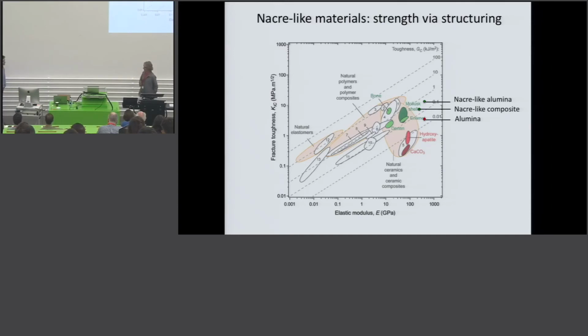Right. So in the case of bone, you also have obviously the challenge of addressing brittleness because you have 50% of the material being hydroxyapatite, right? And bone also uses this concept of structuring the material at different length scales in order to combine strength and toughness, being stiff at the same time being difficult to break. The mechanisms are slightly different in a way that at the smaller length scales you have collagen fibrils, which are oriented in the loading direction, in that sense similar to the seashell. And these are reinforced with hydroxyapatite platelets to make them very strong. So these fibrils, mineralized fibrils, will play the function of the mineralized platelets here, or the mineral platelets.